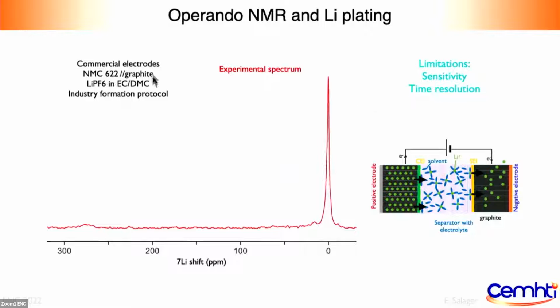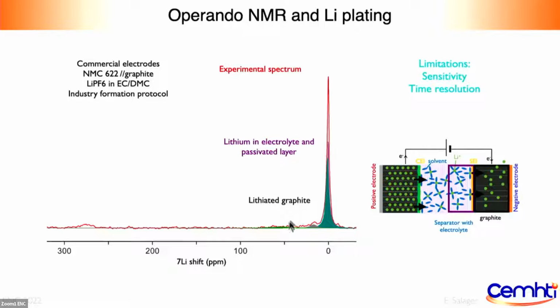So this is what the in situ spectrum looks like. We have signal from lithium in the electrolyte and in the passivating layer. We have lithiated graphite here. And this time we don't need spatial localization because spectroscopically the metallic lithium is in a different place.